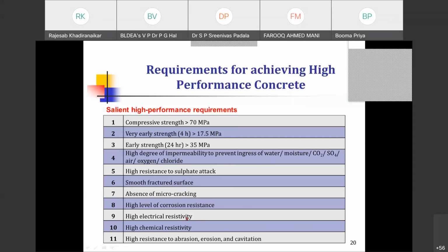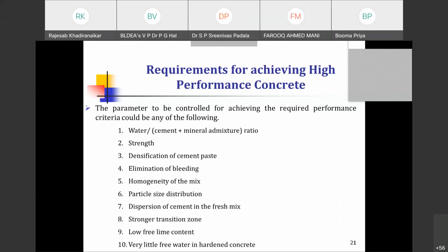Since the diffusivity is low, then definitely it will have a high level of corrosion resistance. Then high electrical resistance. This is another measure, electrical resistance, another technique of measuring the durability or the diffusivity. Then high chemical resistivity, and high resistance to abrasion, erosion. These are the physical phenomena: abrasion, erosion, as well as cavitation. Particularly for hydraulic structures, spillways, and all that, you can effectively use this material because of the reduced cavitation effect. So all these were the characteristics of high performance concrete, and now the question is how to achieve these characteristics.